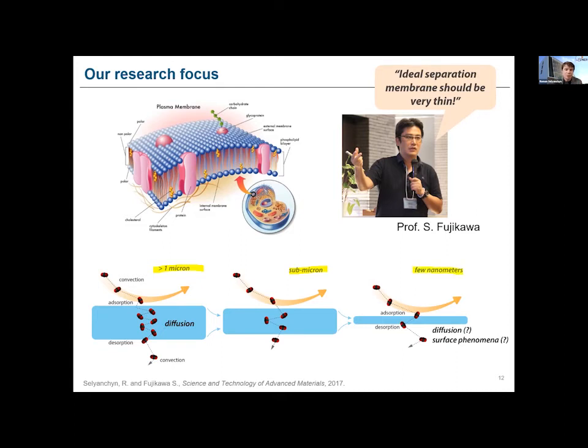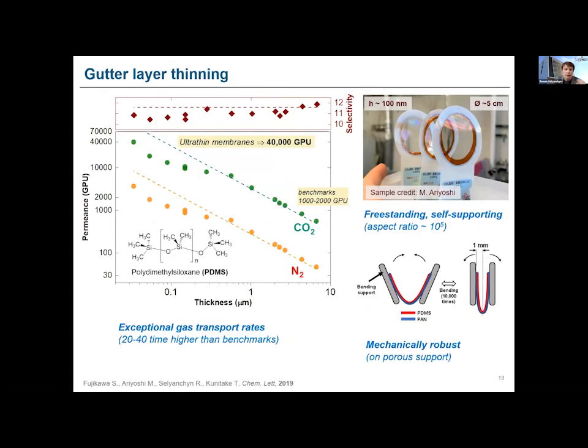And by thinning, we aim to step up into the area in which the properties of the membrane will be changed, and diffusion as a main rate limiting factor of gas transport through the membrane is diminished. And the properties may be governed by some surface phenomena on which we can rely. And of course, we don't have to forget that membranes, in addition to high permeance, should be defect-free and very highly selective. And recently we have demonstrated that thinning can indeed lead to breakthroughs in membrane performance.